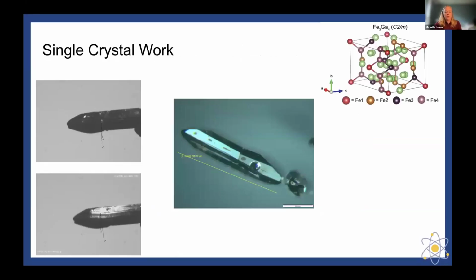In the single crystal work, we were growing the crystals using a 2-zone furnace, with iodine and a ratio of iron and gallium, and we were able to grow the single crystals along the B-axis. So the long axis is the B-axis, and the A and C are related to the facets that you see in the crystal. After we grow it, we can get really large crystals that are almost 800 microns, but we want to keep them a little bit smaller since around 600 microns, they tend to twin, as you can see on that little surface right there.